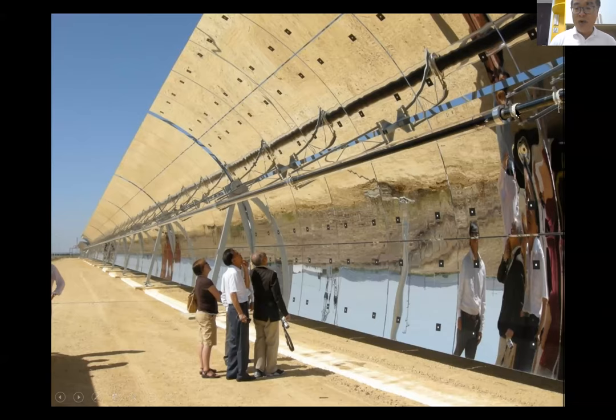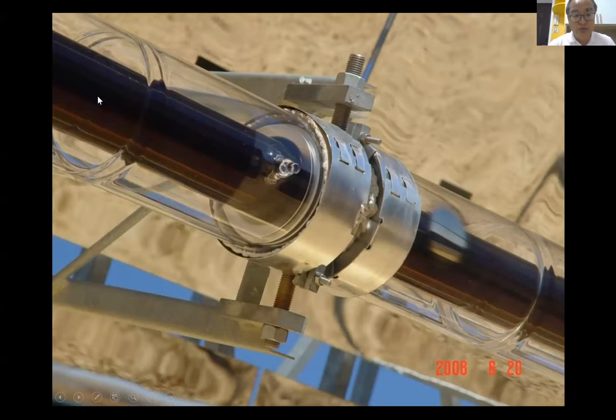And what we are working on in my laboratory together with the company is to fabricate and coat such tubes, very high temperature tubes with solar spectra absorbing coatings. That is, they can resist temperatures as high as 500 degrees. These tubes are used with parabolic trough collectors, which focus sunlight onto the tubes and can reach more than 400 degrees and so on.